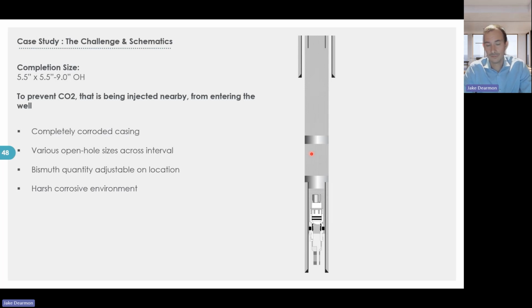So what we were able to do is start with going into the well and removing the existing cement plug and doing a log. And during that log, we found that 20 meters of 5.5 was not only corroded, it was completely removed. And that was the 20-meter formation interval that CO2 was traveling in. So the only way to protect the wellbore both below and above was to set a bismuth plug below that charge formation interval and then another one above it.